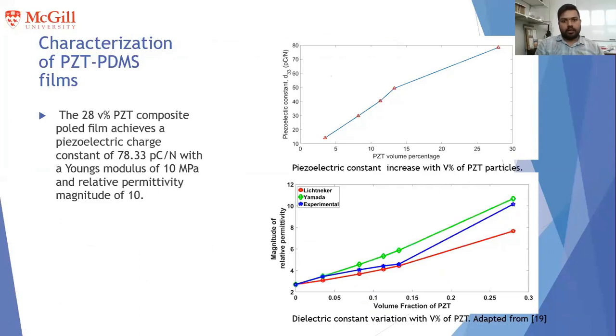And coming to the characterization, you can see we have measured both piezoelectric constant and dielectric constant for all different volume percentages of films. These results are from our other article, which is already published in IEEE Sensors. So we were able to achieve 78 picocoulomb per Newton.